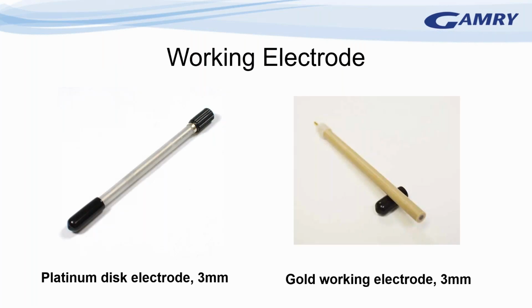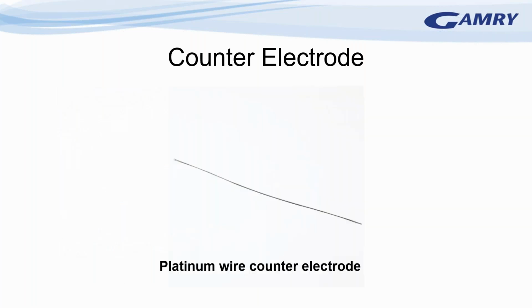So the working electrode or sample electrode is either an inert metal where the electroactive compounds are going to be reacted, or it's a material that has properties of interest. Common inert electrodes are platinum, gold, or glassy carbon, and may come in electrodes like the ones shown, where you have a polished disc that's exposed to the solution. The counter electrode also needs to be of an inert material, where reactions are facile. Platinum is a common material, like the wire that's shown. You may also want to have a larger surface area electrode, so sometimes a platinum gauze is used, and platinum is easy to use because it's easy to clean.